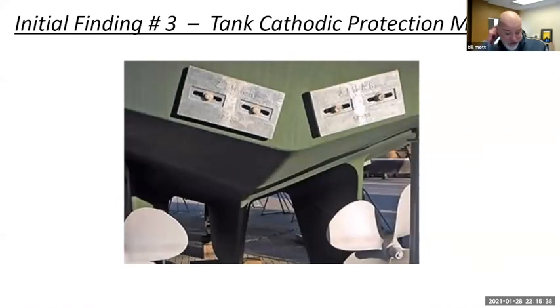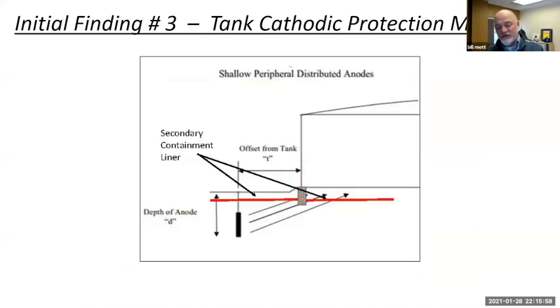Next thing I'd like to talk about is cathodic protection. Most of you are actually probably familiar with that. They use them on boats all the time. These are zincs for the back of a boat, and it's bolted to the boat, so it's probably an aluminum or steel boat, and these are probably zinc anodes, and they provide a current that keeps the bottom of the boat from corroding. Well, tanks use the same exact science. Some operators are able to install perimeter anodes like this that drive current up to the tank bottom, and they can protect the tank bottom in that manner.